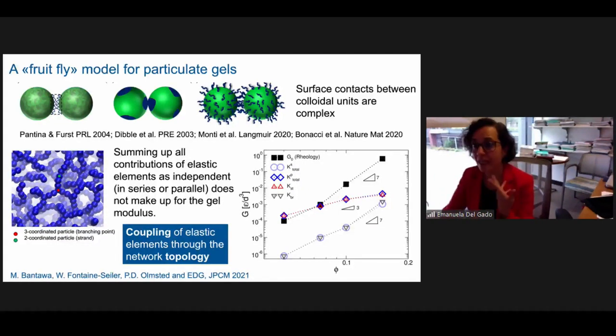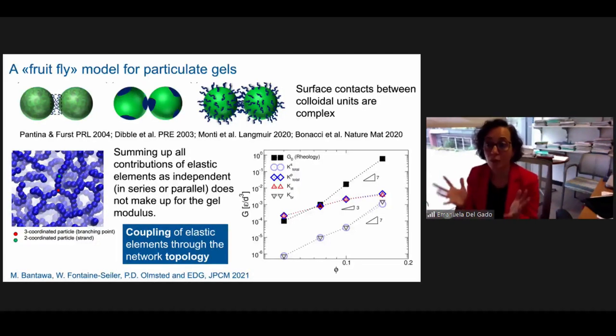So this tells us that indeed the topology plays a very important role in what is the part of the structure that determines the mechanics of the system, that it's not just by identifying what are the structural elements that are there that we can actually come up with the prediction of what's the modulus of our gel, especially when these materials become more and more coupled, which is what happens with the emerging frustration in the gel as it increases with increasing, for example, the volume fraction of the system, or as it could happen in experiments by changing the way I prepare my gel, the kinetics of gelation. And so then basically this tells us that again, the topology plays an important role in determining what is the structure that is ultimately important for the mechanics of it.